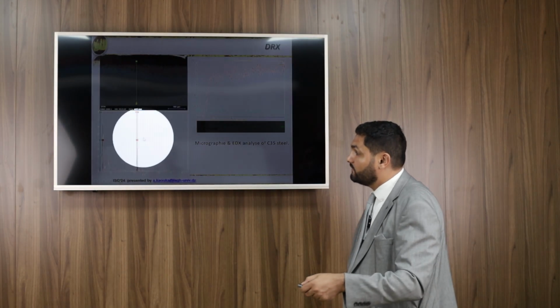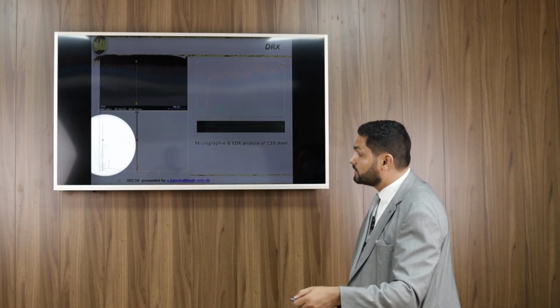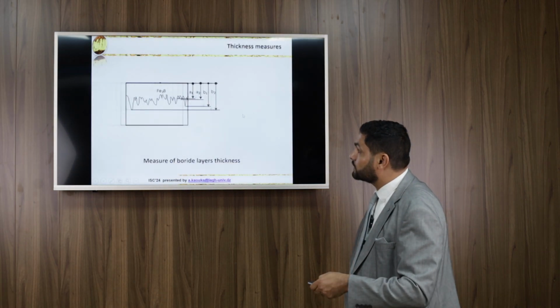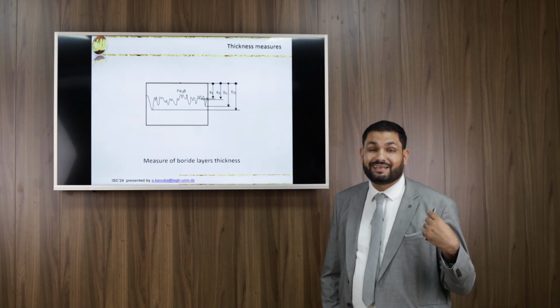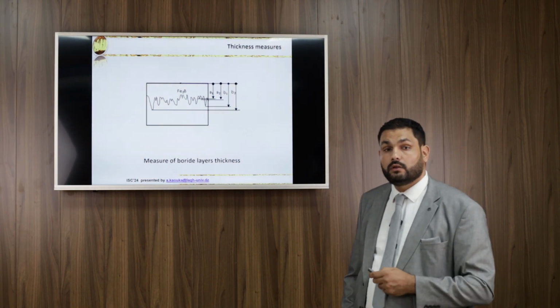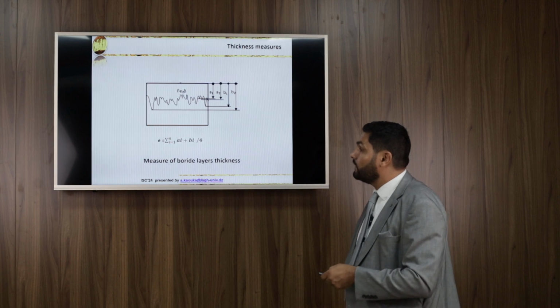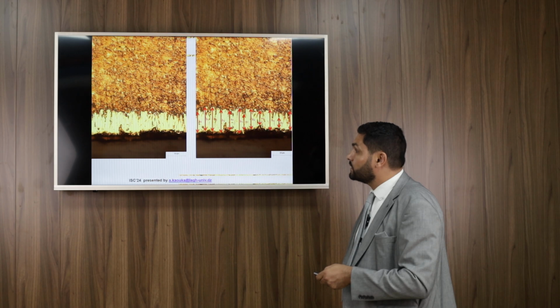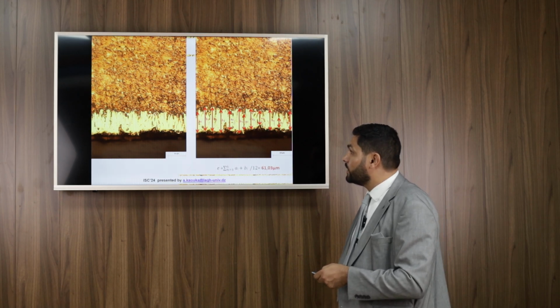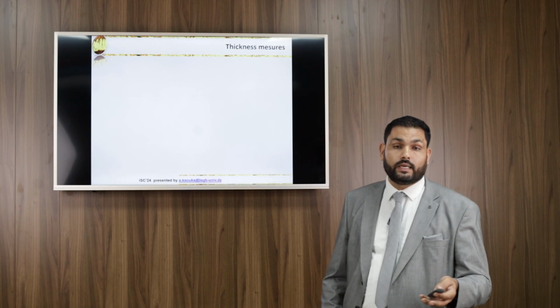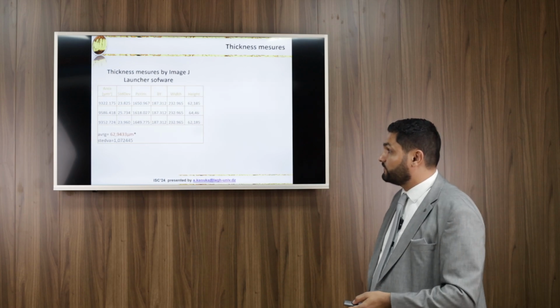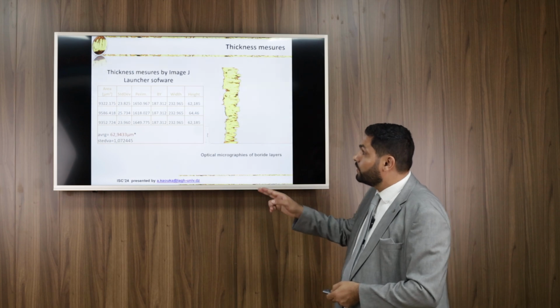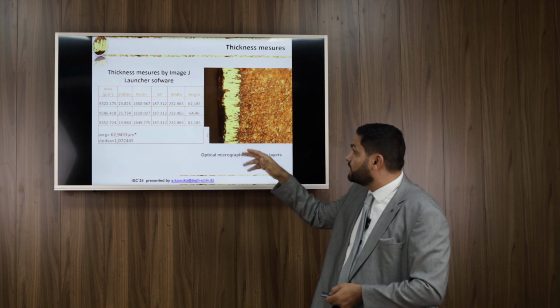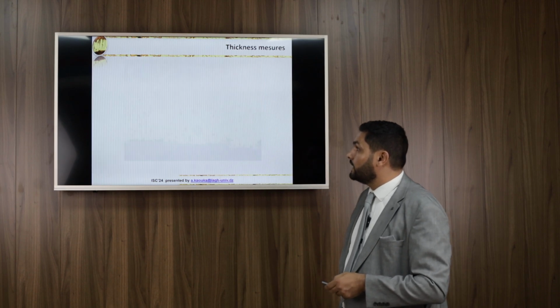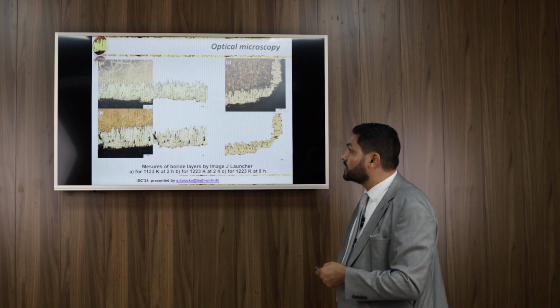For iron, we confirmed that we clearly have iron and a little bit of carbon and less of boron. So we measure the thickness of boride layers with the classic and old method that we have in the literature, with the average of 4 measures of boride layers. For example, this is about 61 micrometer. And we propose another method using Image J Launcher software. It's free software, you can download it on the internet easily. With this software we can measure the width, the height, and the area of all boride layers formed, and calculate the substrate at different temperature and time.